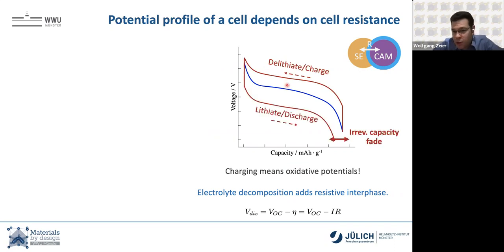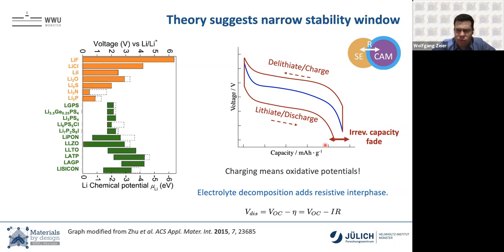When you discharge your material, you get some sort of overpotential. If you now start decomposing your material, you build a resistive interface. This gap becomes larger, which means the energy that you get out at the end is a lot less than what you put in. So you're constantly losing energy. And you might actually kill capacity because you're breaking apart your active materials as well. So decomposition is a bad thing in principle.